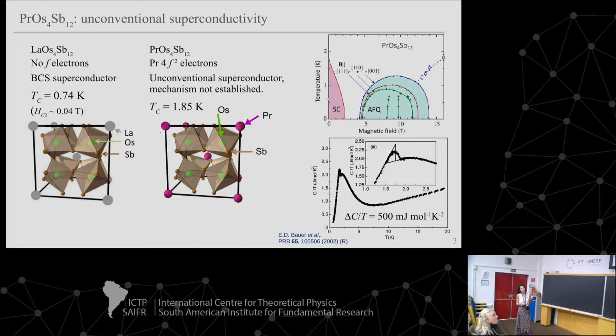So this is going into the superconducting phase, and delta C over T, so the Sommerfeld coefficient extrapolated there, is about 500 millijoules per mole Kelvin squared. So it's really heavy fermion.